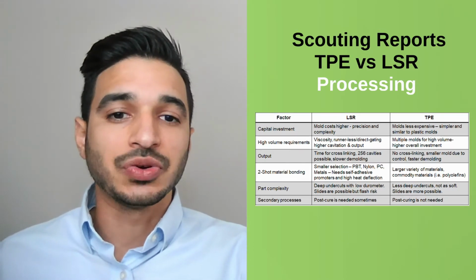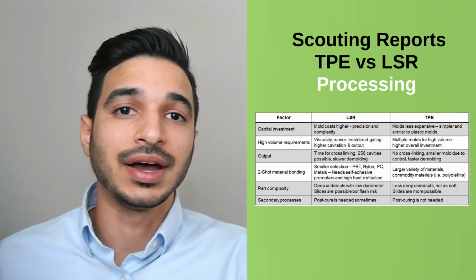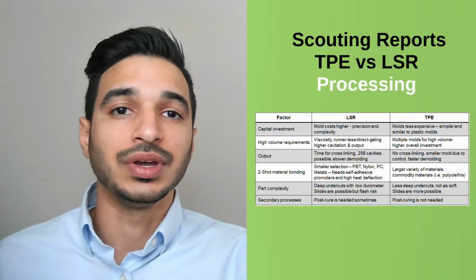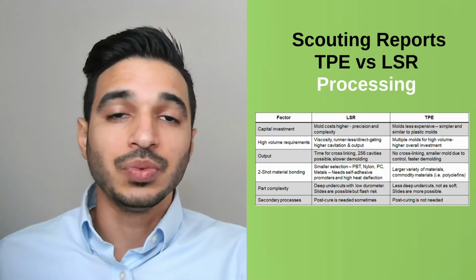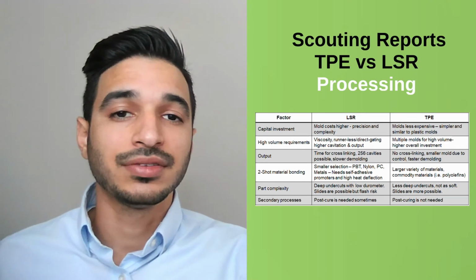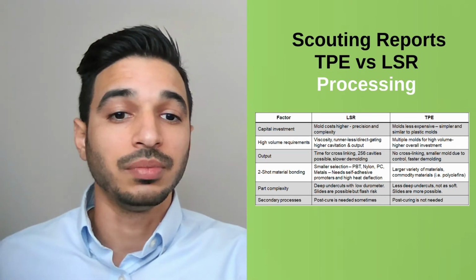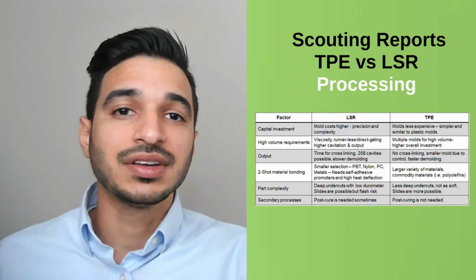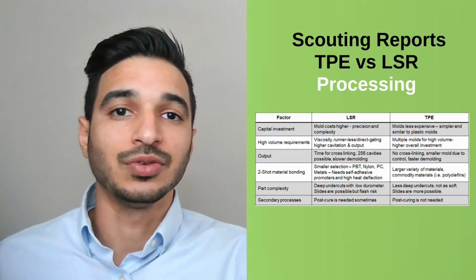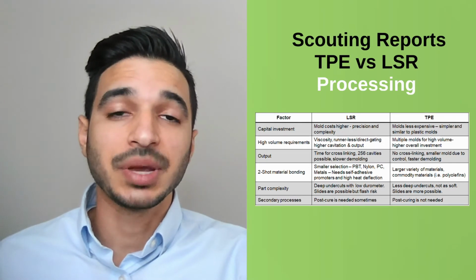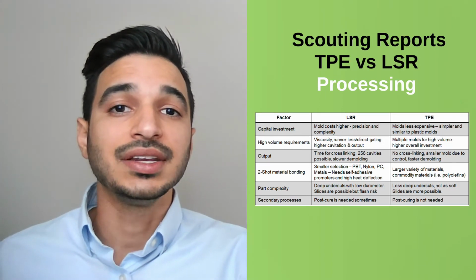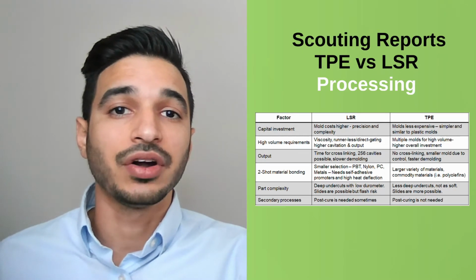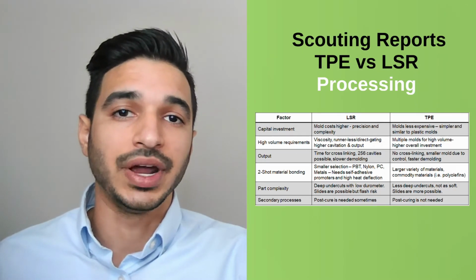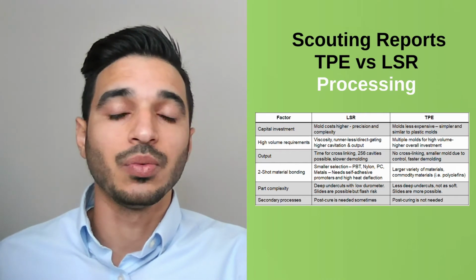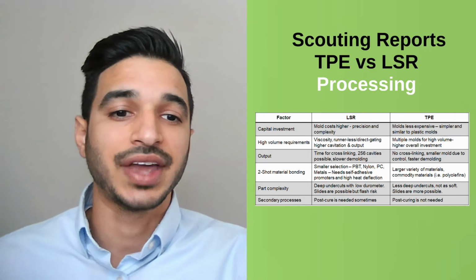When it comes to two-shot material selections, both of them have opportunities to bond to either plastic or metals. However, LSR is more limited in that scope. Traditionally, we use PBT, nylon, polycarbonates, and certain metals like stainless steel or aluminum. However, we need self-adhesive promoters within the material to bind to those substrates. And also, those substrates need to have a high enough heat deflection temperature, typically above 140 degrees Celsius or 280 degrees Fahrenheit, to ensure it does not warp or get damaged in that LSR cavity.